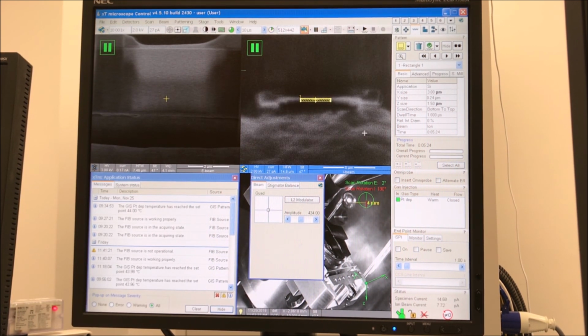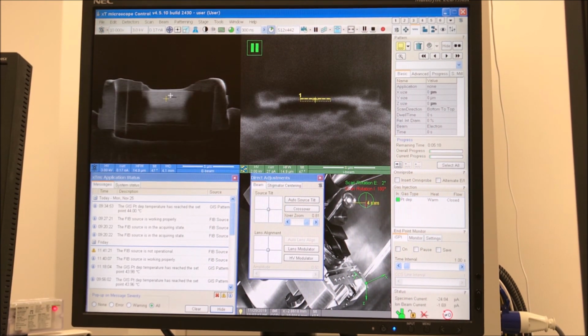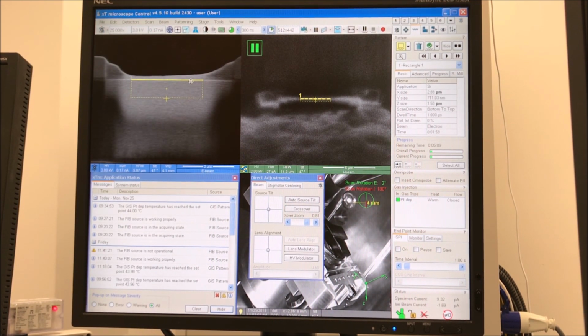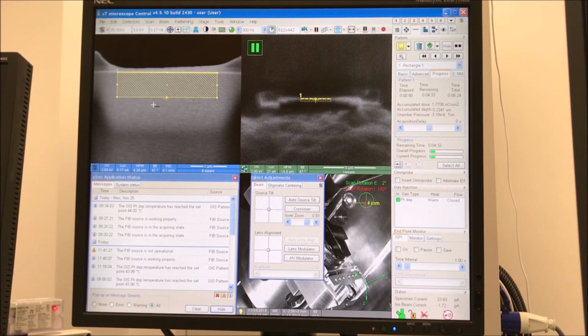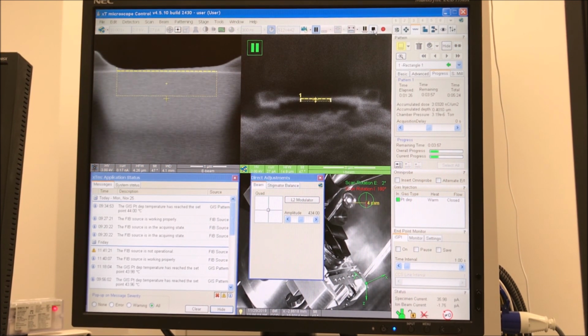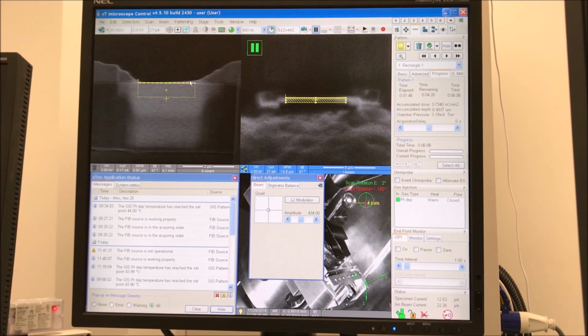You want to be really careful here, especially with your last steps. So I went ahead and started it. Okay, there's my indicator box again. So I still have stuff above that top yellow line. So I basically want to keep going until I have just a little bit of stuff above that top line, because then I know that I've made it as thin as I can while not getting rid of the surface. And so right about there.